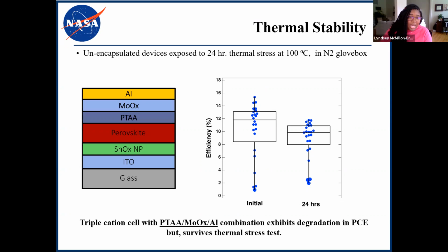In the second case, we're looking at an unencapsulated device that has PTAA and molybdenum oxide with an aluminum electrode. And this one exhibited some degradation in power conversion efficiency, but it performed really well in this thermal stress test overall. And this was the one that we had hypothesized would probably do the best. And again, that organic material is kind of encapsulated or shielded by the metal oxide and aluminum.